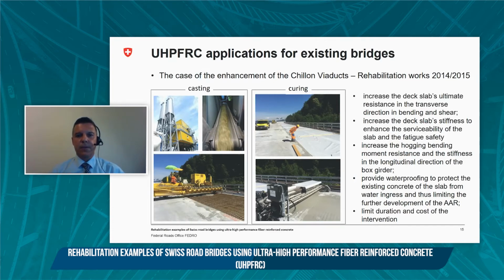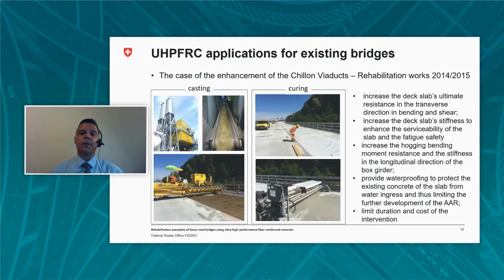Increase of the deck slab's ultimate resistance in the transverse direction in bending and in shear. Increase of the deck slab's stiffness to enhance the serviceability of the slab and the fatigue safety of the existing reinforced concrete elements in view of future high traffic demands in number of vehicles and axle loads. Increase of the hogging bending moment resistance and the stiffness in the longitudinal direction of the box girder. Provide waterproofing to protect the existing concrete of the slab from water ingress and thus limiting the further development of the alkali aggregate reaction. Limit duration and cost of the intervention by realizing all the above listed requirements and structural effects by casting of just one layer of ultra-high performance fiber reinforced concrete.